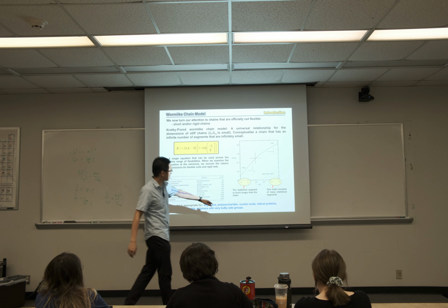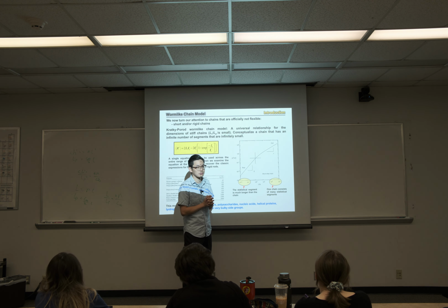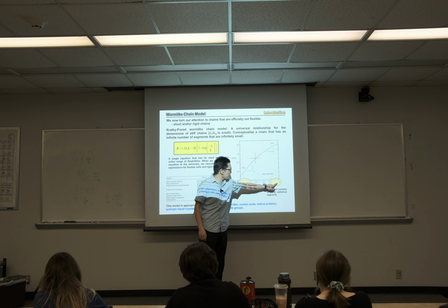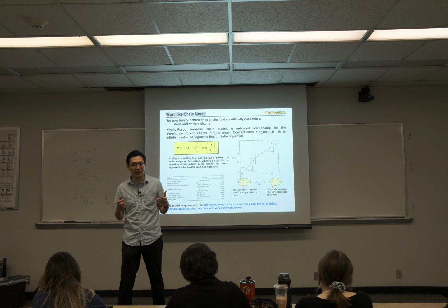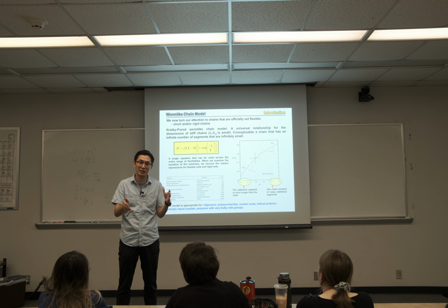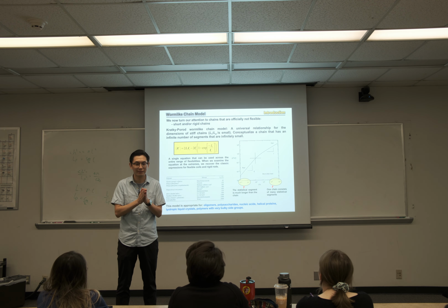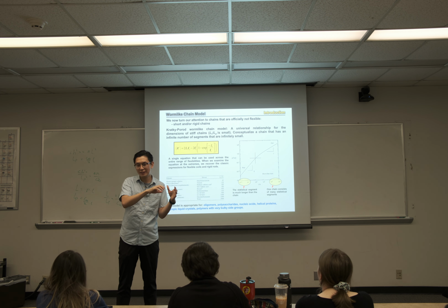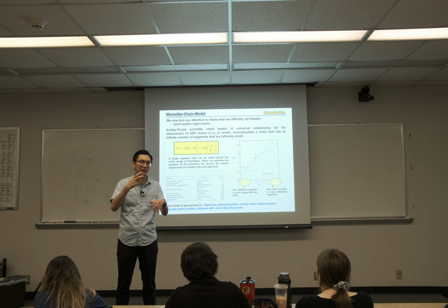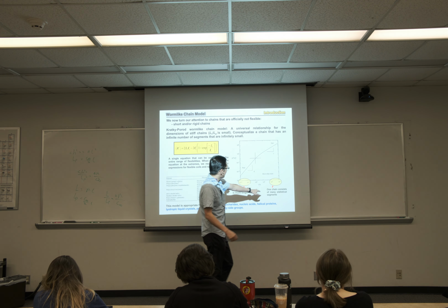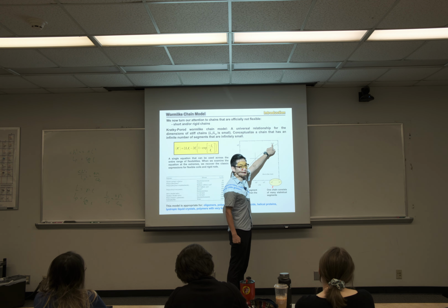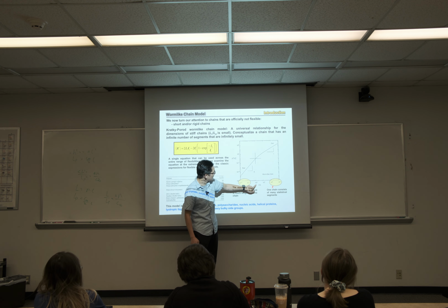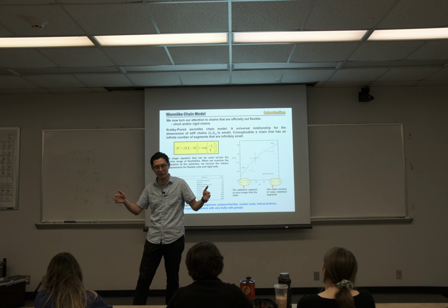Contour length is the total length of the chain. LP is how long it takes to bend. So if L divided by LP is a large number, let's say 100 or 1,000, that means your chain is much longer than the segment it takes to bend. 1 LP is the length taken to bend. If your chain contour length is 1,000 of that, that means there are a lot of twists and bends along the backbone. So these are typically the coil-like chains that we see. But at the other extreme, when L divided by LP equals 1, that means contour length and persistence length are the same.